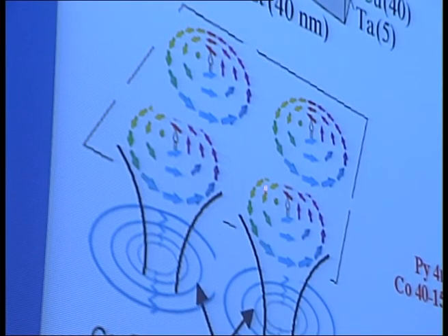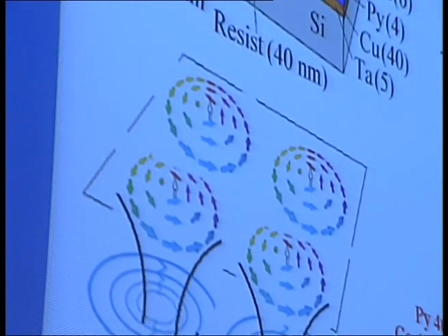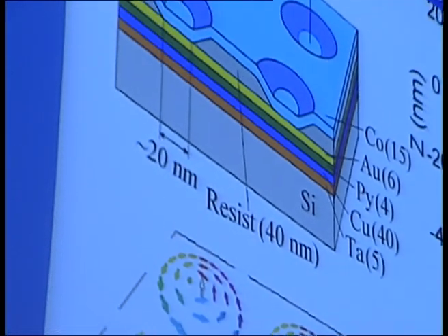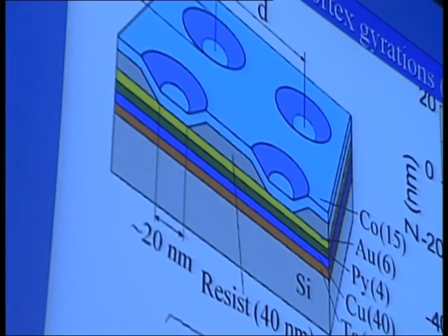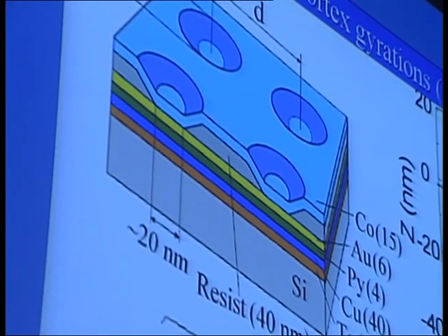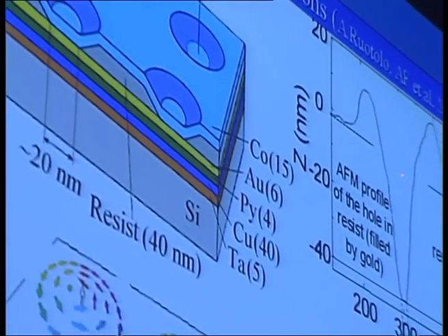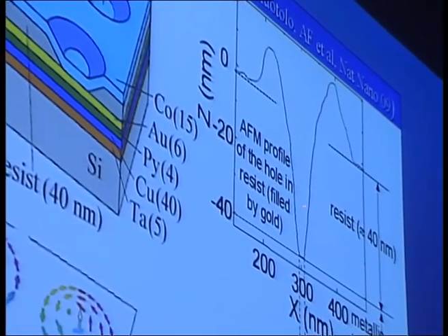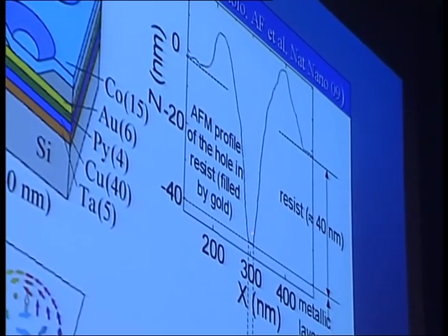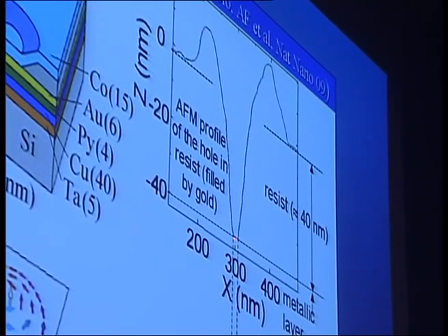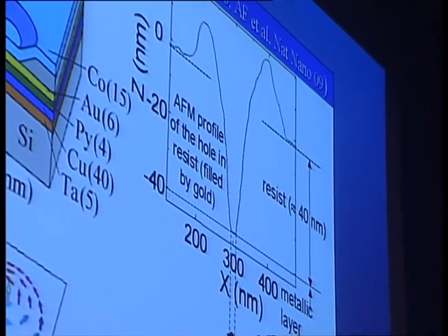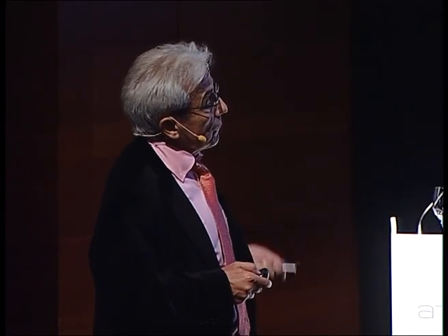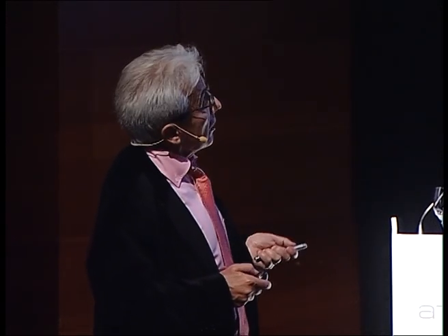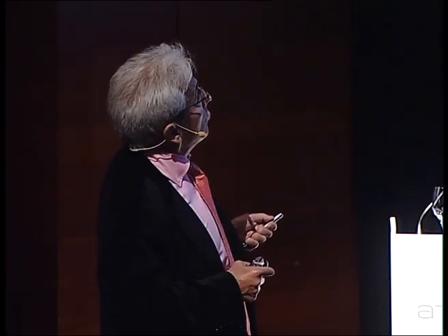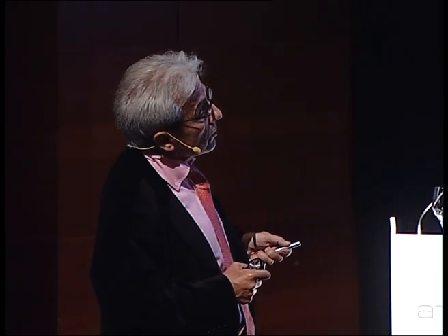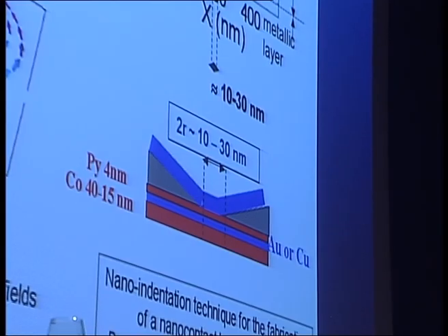And I can say a few words on nanotechnology. We can obtain very small nanocontacts by nano-indentation with an STM of a layer of resist on the multilayer this way, and then the depth of the penetration is controlled by a resistive control to go just at the top of the multilayer, and then one fills with a magnetic material to obtain this sort of structure. So this was simply a comment on the technology, that you can see that this type of technology allows to prepare nanocontacts of only 10, 20, or 30 nanometers.